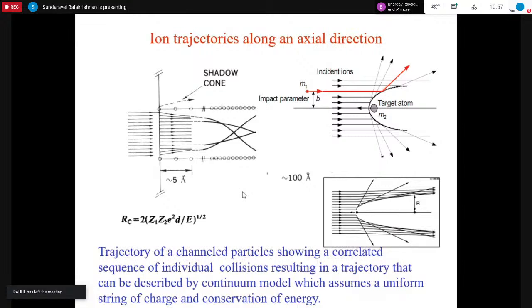And as such, when the incident beam is aligned with respect to this axis, there is only a small angle collision between the string and these atoms. How close this incident ion can go to this incident string is of the order of this RMS thermal vibration amplitude, which is of the order of 0.1 angstrom. So the sensitivity of this technique is something like 0.1 angstrom.